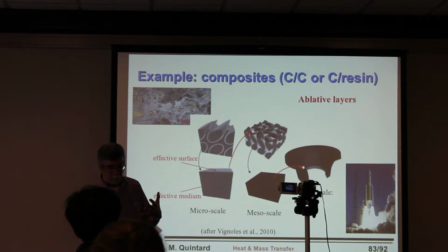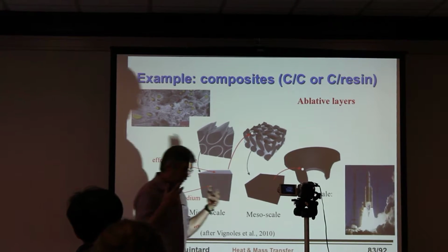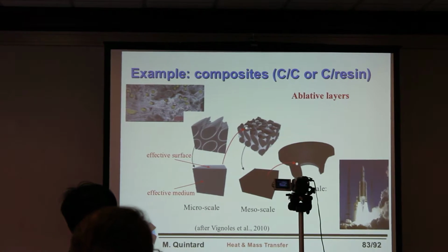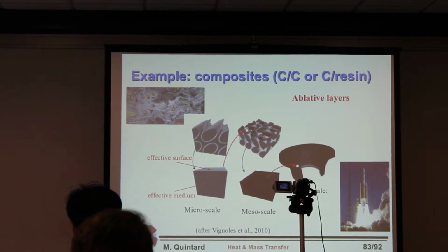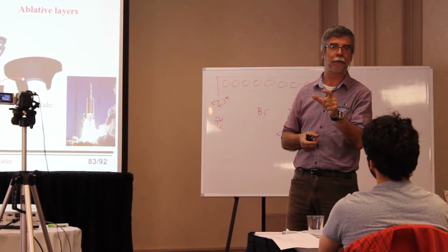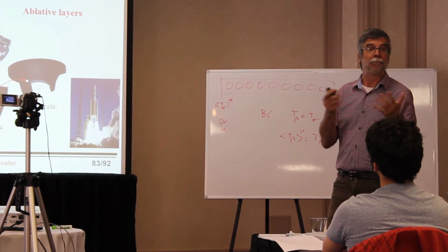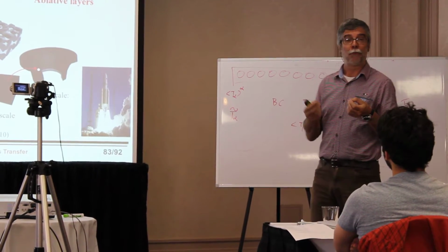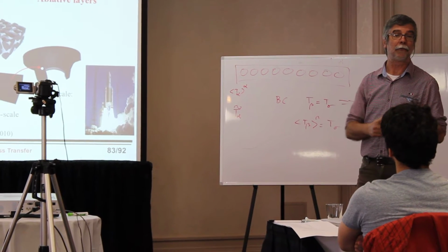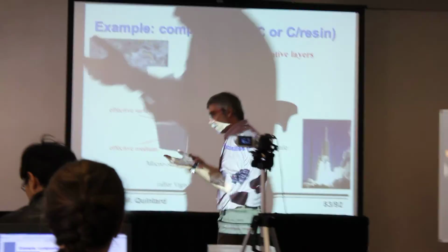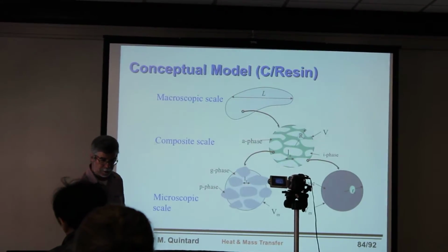You probably understand that. The life of an ablative layer in a rocket is how much? 1 minute? 2 minutes? So you have a change in temperature which is enormous, 2,000 degrees, over a relatively thin layer. And so local equilibrium modeling might not work. And if you have a process like that, you have, of course, the heat transfer, but you have the pyrolysis of the material, you have mechanical problems, so you want to understand that. So I'm just illustrating using one of the slides. So we work on that.